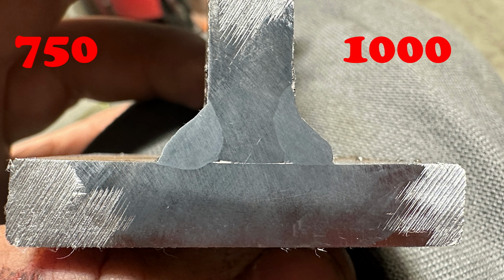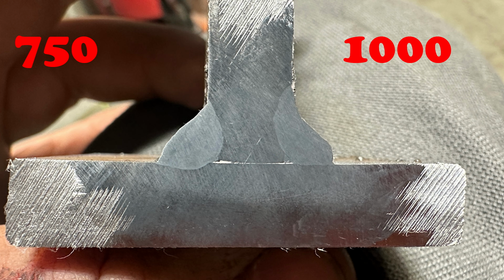So the 750 degree looks much like the room temperature plate. It just has a little bit more fusion in the upright plate, but the root fusion at the bottom isn't really anything better. You can see it's not really a lack of fusion, but you can watch that line on the bottom plate, and it really didn't punch in there that much better, I would say. Again, the upright plate is a little bit better.